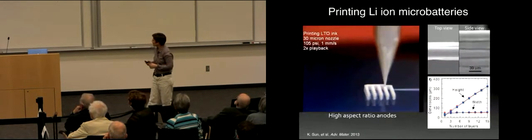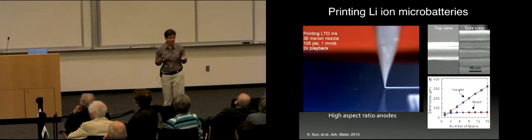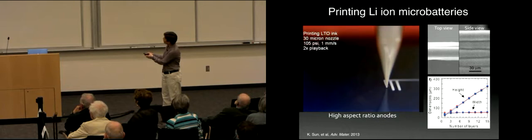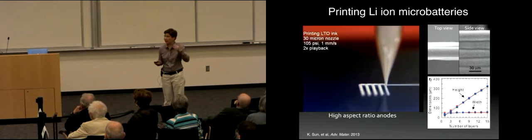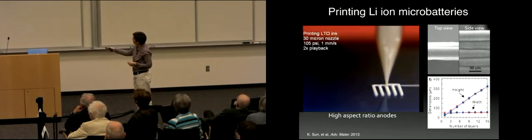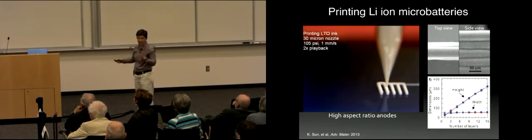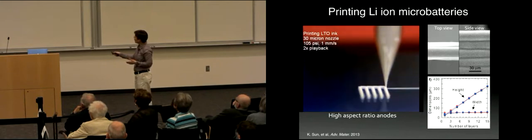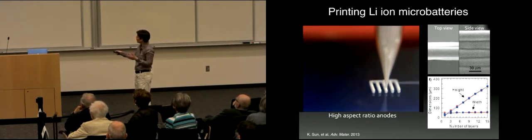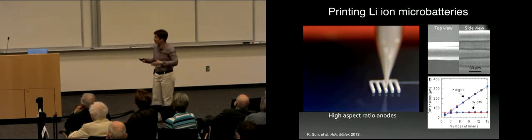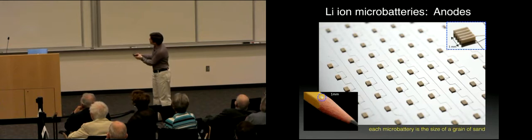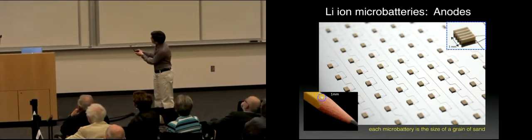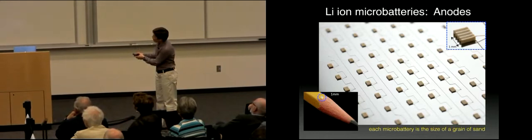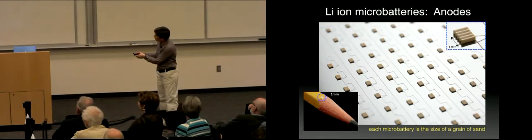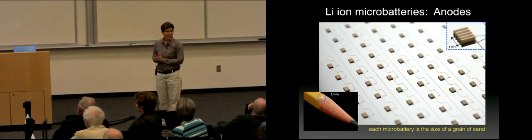So this is just an example of us printing one of the anode architectures. Again, because it's a filamentary process, we can build something where if you look down at this wall, it's very narrow. It's a 30 micron nozzle. Again, a third of the width of the human hair. We're building up layer by layer so we can create batteries that have very high aspect ratio walls, and then a width that remains whatever the print nozzle being used. As we add layers, we add height, but we don't make it wider. Once we've printed all of these little anodes, we can come in and interdigitate the cathode inside these teeth. Just to give you a size scale, that's our little battery right there. It really is very small.